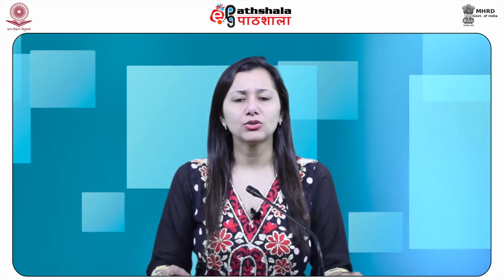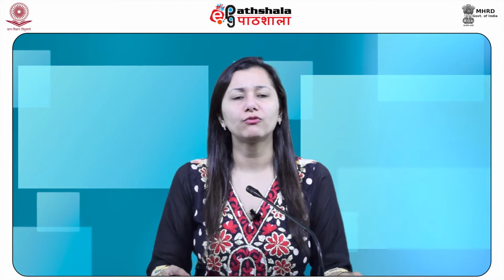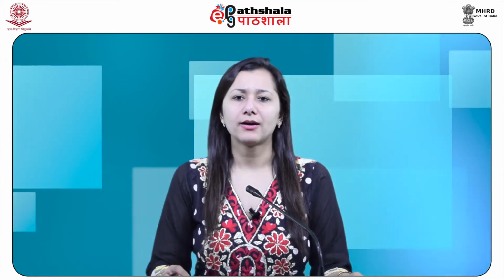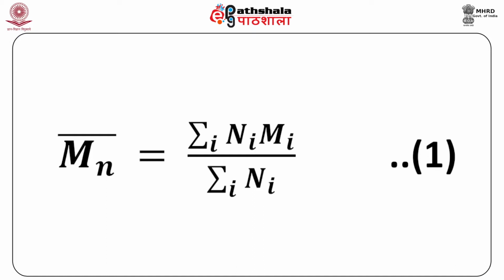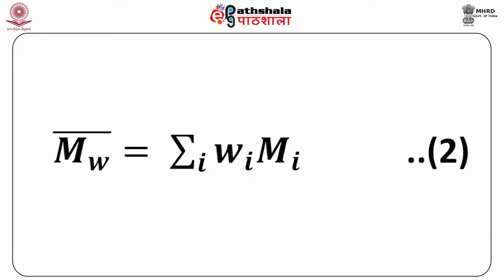Some of the commonly used averages for describing the distribution of molecular masses of polymers are as follows. Number 1, number average molar mass, Mn bar equals summation Ni Mi divided by summation Ni, given by equation 1, where Ni is the number of molecules each having molar mass Mi. Number 2, mass average molar mass, Mw bar equals summation Wi Mi, given by equation 2, where Wi is the mass fraction and Mi is the molar mass.